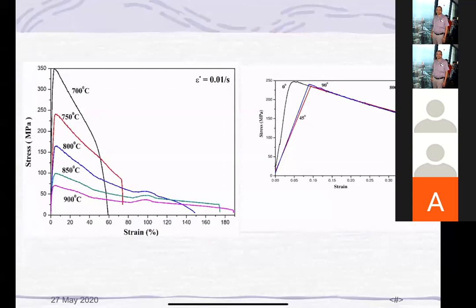Now see, at strain rate 0.01 per second, see how the stress strain diagram behaves. At room temperature, titanium grade 5 material doesn't have good ductility, maybe 10%. But here, at 700 degrees centigrade, it is close to 60%. And this is the yield point. The yield strength at room temperature is also quite high. Depending upon the exact composition, it will vary from 800 to 1200.